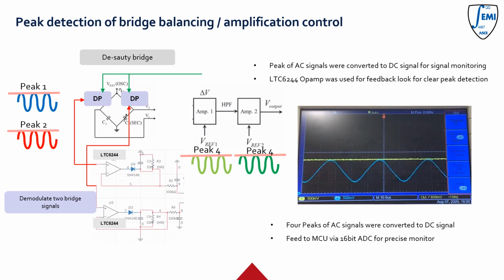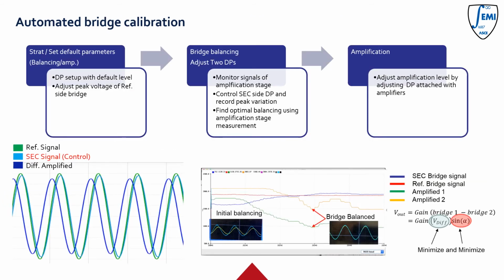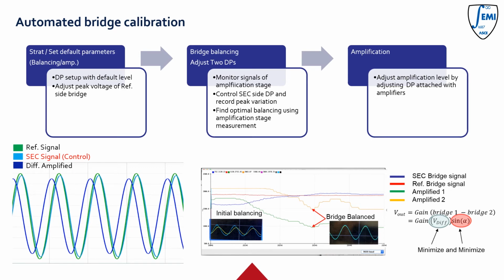The video shows that the blue signal is a 32 kHz sine wave and the yellow signal is a peak-picked signal converted to DC component. Then, the peak voltage values are fed to the 16-bit ADC and microprocessor to monitor the peaks of the sine signals. By using the peak voltage measurement, an automated de Sauty bridge balancing algorithm was developed.